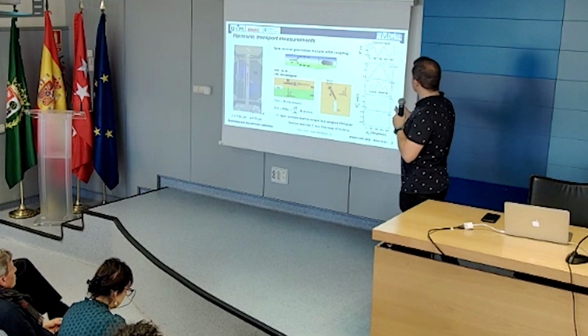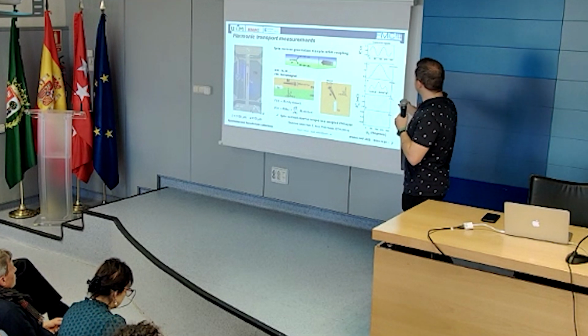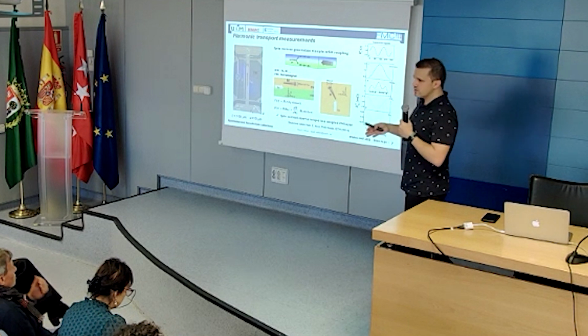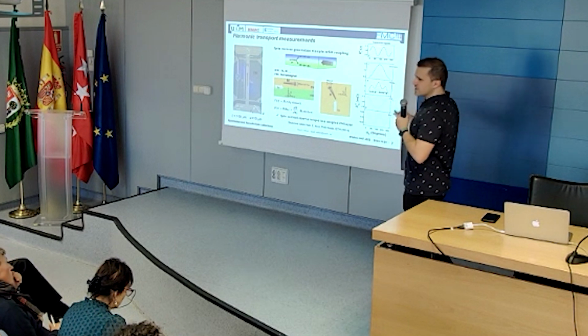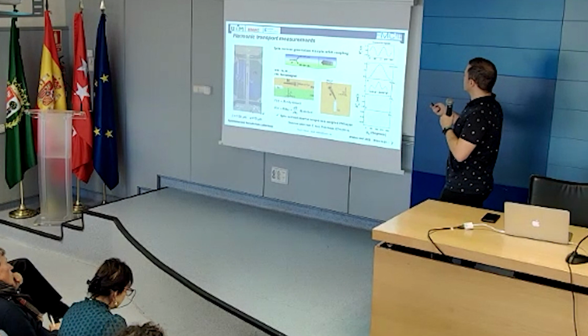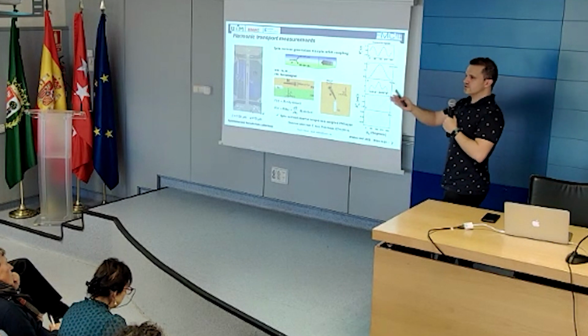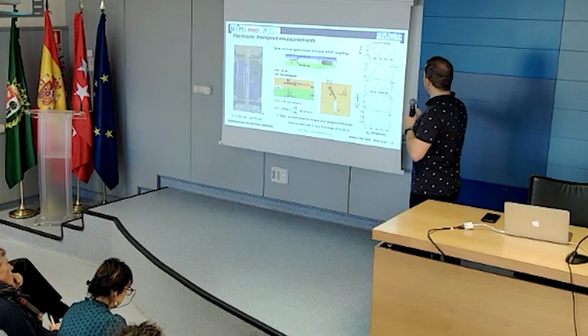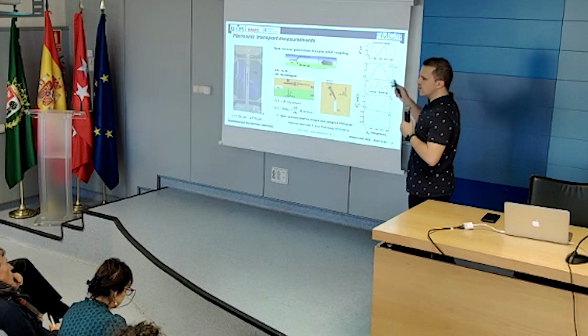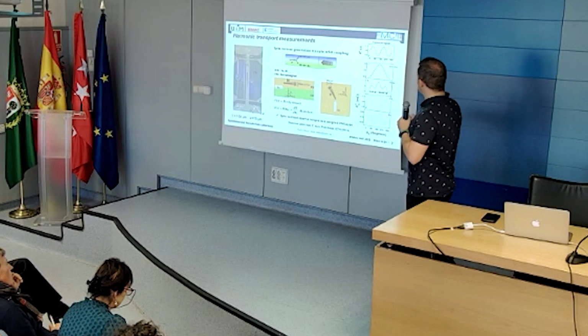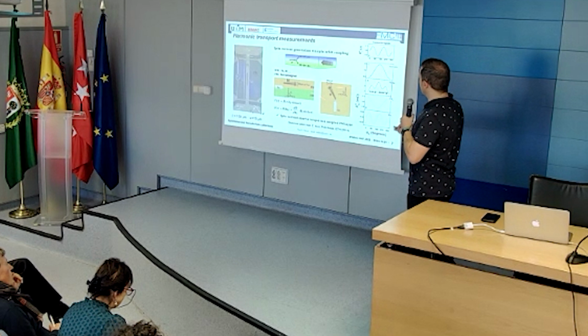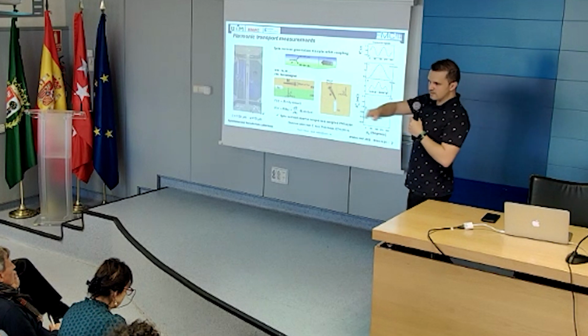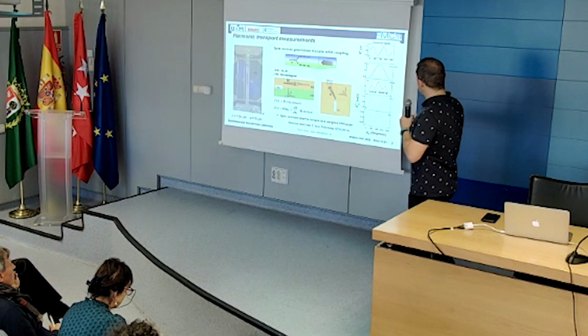So that's how, for instance, a Hall measurement looks. That's called the planar Hall effect. Maybe you're familiar with this, maybe you're not, but that's how it looks. These tracks show where the magnetization is pointing, and that's simply assigned to an angular dependence. But then you have these torques that I'm talking about, which have their own particular angular dependences. These are the anti-damping-like torque. Here we are rotating the magnetization in the plane, right? So that's what you are getting.